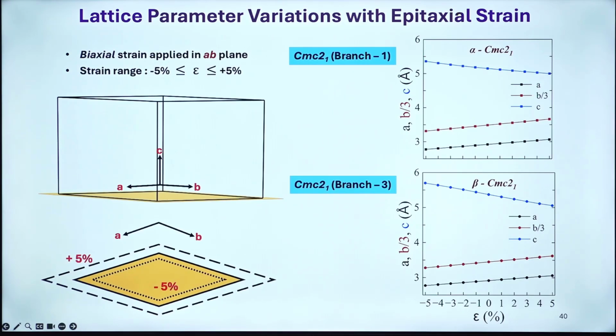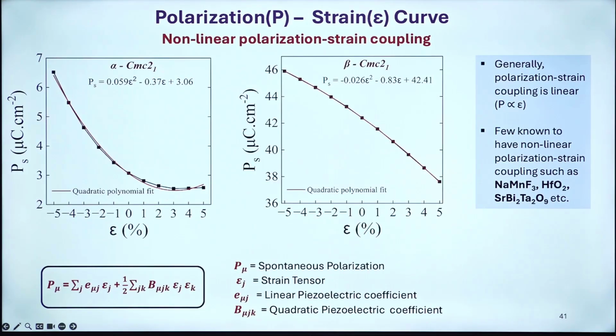So then we tried to have, with respect to epitaxial strain, we are trying to take branch 1 and branch 3, because branch 2 and 4 are not of interest to us. Then we tried to have a positive and negative value of strain, and then we tried to see how these lattice parameters behave with respect to strain. Okay, so this is the epitaxial and biaxial strain we say, both compressive and tensile. I will show how the polarization behaves.